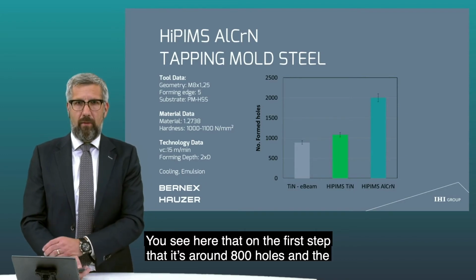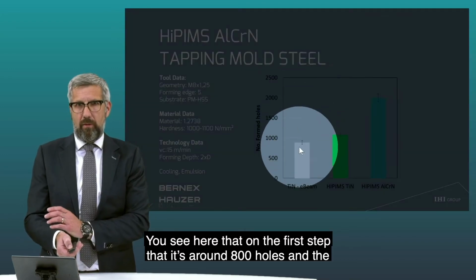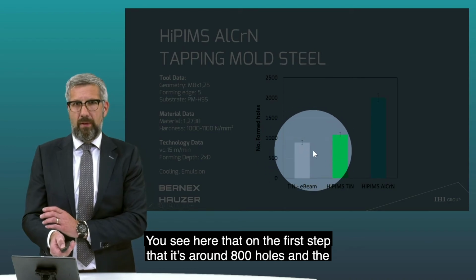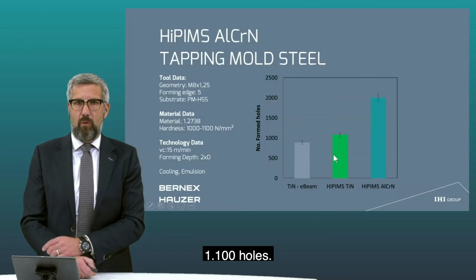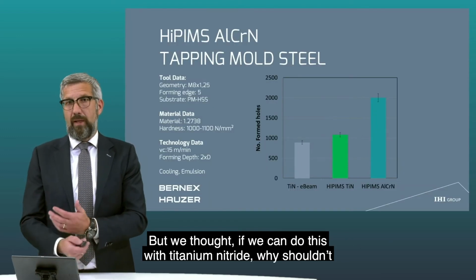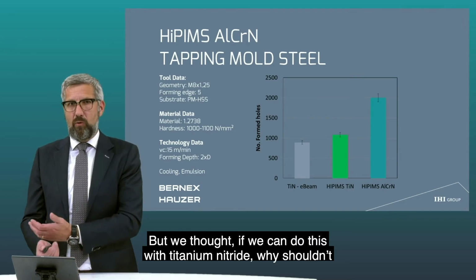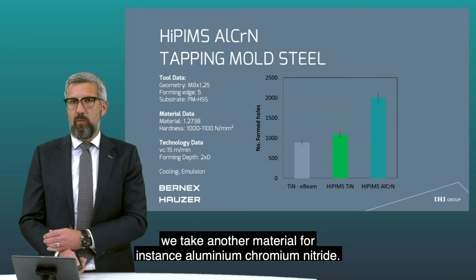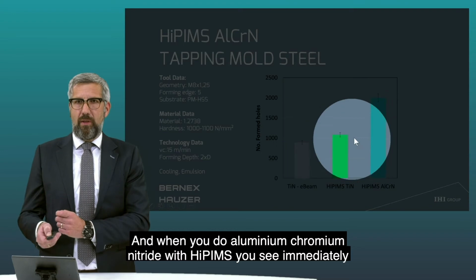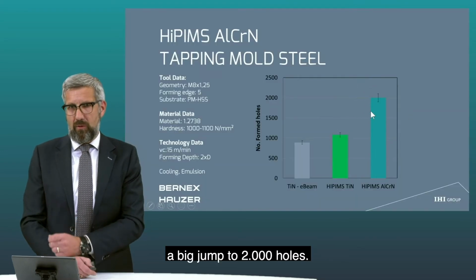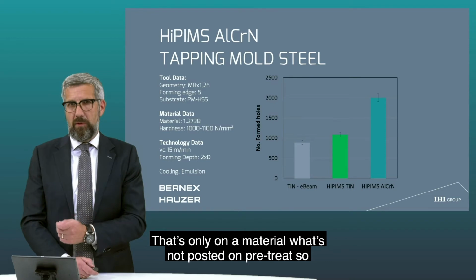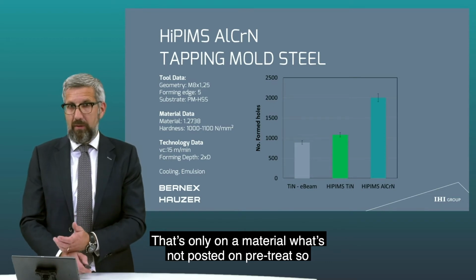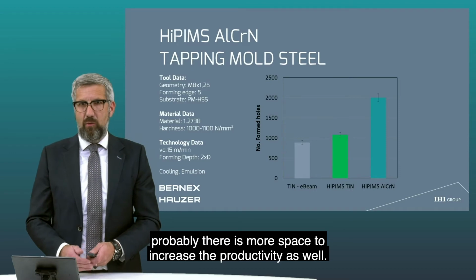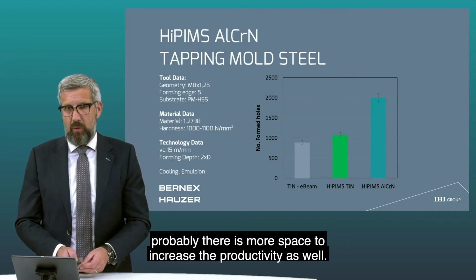You see here that in the first step you have about 800 holes, and the second step with the HiPIMS titanium nitride you get to 1100 holes. But we thought, okay, if you can do this with titanium nitride, why shouldn't we take another material, for instance aluminum chromium nitride? And if you do aluminum chromium nitride with HiPIMS, you see immediately a big jump to 2000 holes. And that's only on a material which is not pre- or post-treated. So probably there is more space to increase the productivity as well.